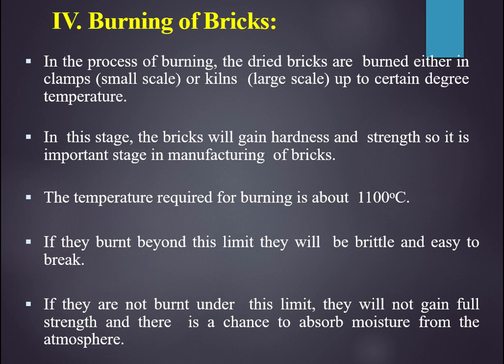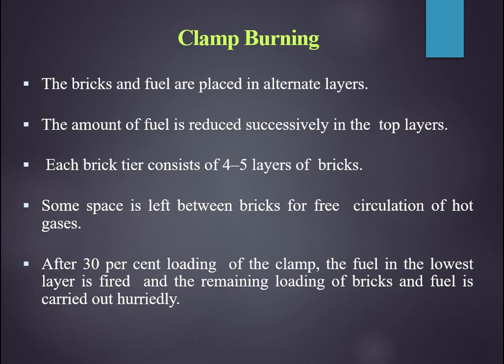So you cannot over burn a brick, and you can't under burn a brick either. If you are not burning the brick properly, it may still have moisture content in it, and once it is used as a building material, it will try to absorb moisture from the atmosphere. So one has to take care that there is no under burning as well as no over burning.